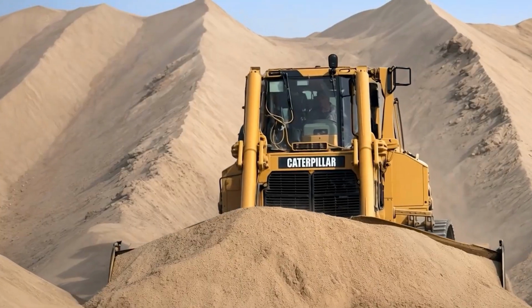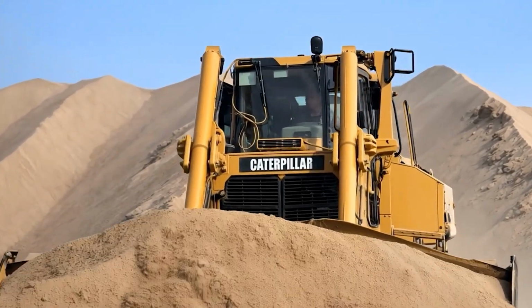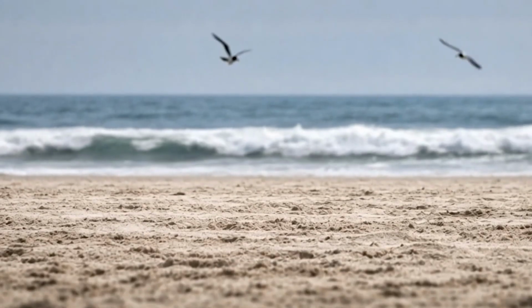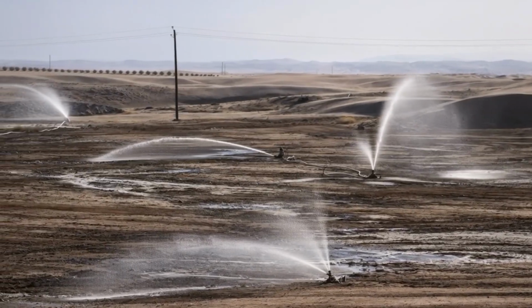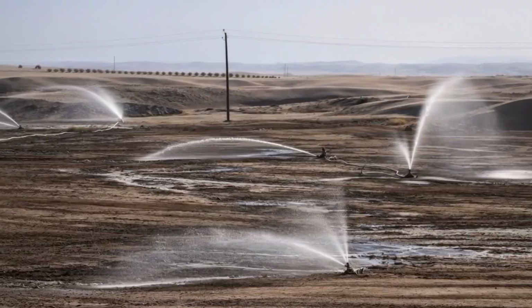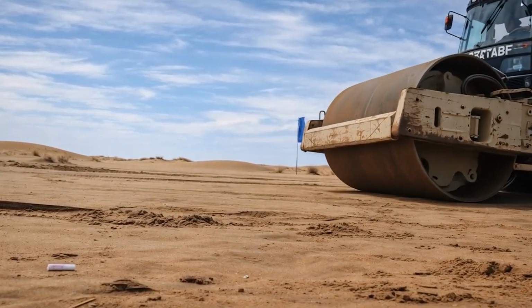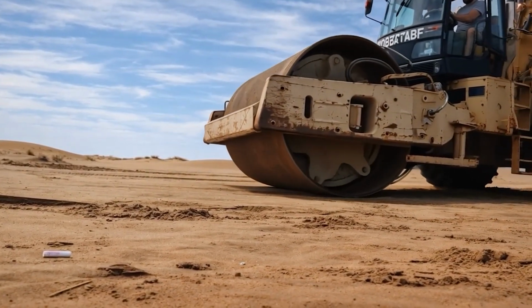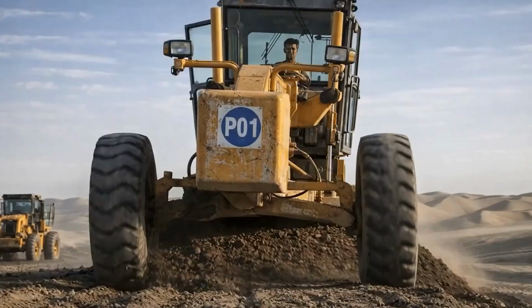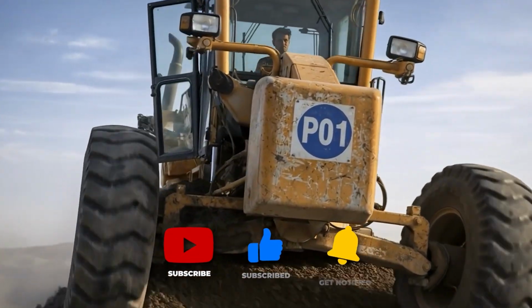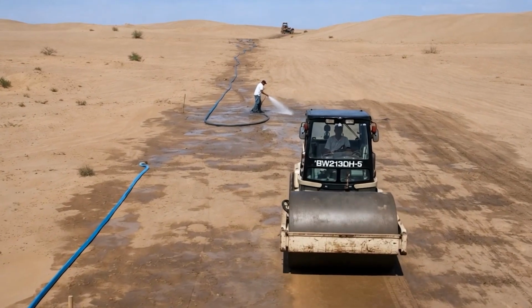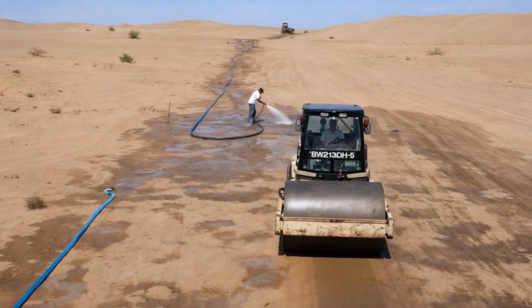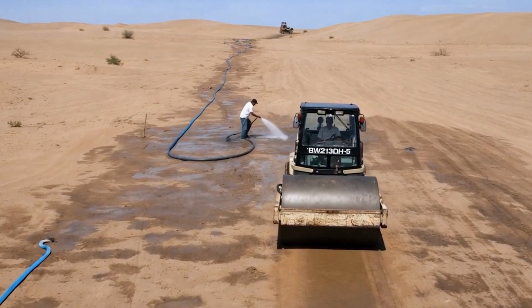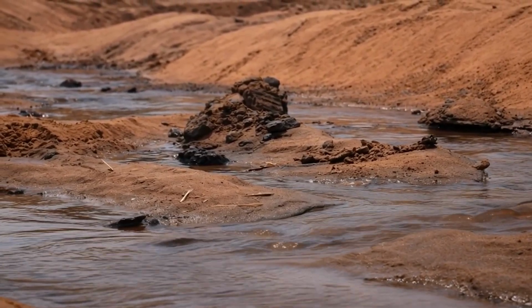It turned out that with controlled moistening, grains of sand bind to one another, forming a denser and more stable layer. Long irrigation installations and underground pipelines were deployed across the entire site. With their help, groundwater was evenly distributed over the surface, penetrating several centimeters deep. As soon as the moisture reached the required level, heavy rollers went to work. Steel drums passed over the same section again and again, squeezing out air and fixing the sand particles.